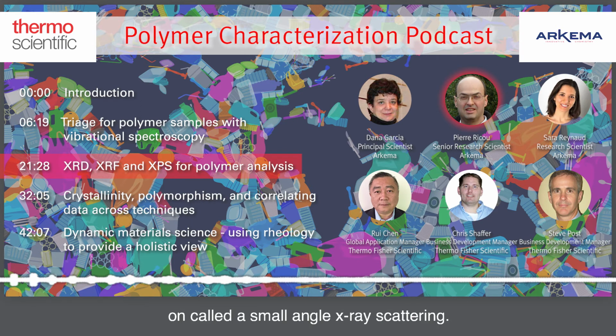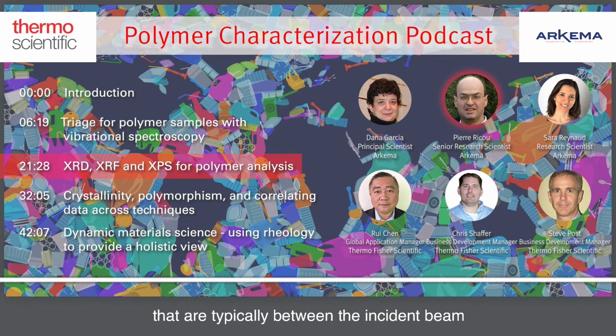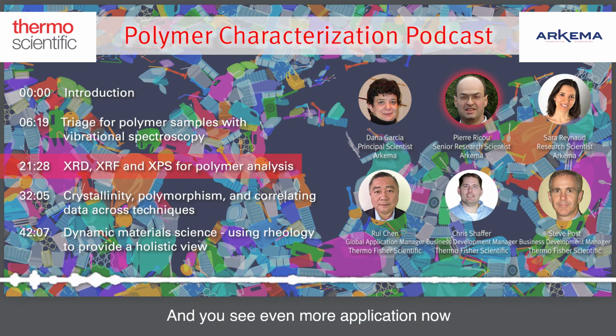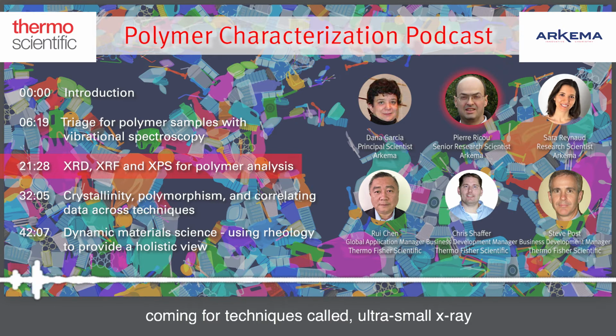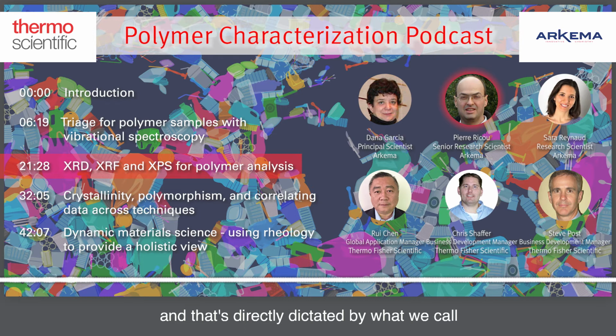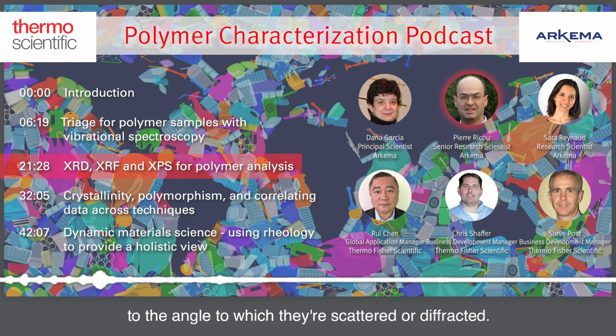A sister technique I want to briefly touch on is called small angle X-ray scattering. So wide angle, as it speaks, you're looking at large angles. Small angle, you're looking at angles that would typically be between the incident beam and a few degrees at most. And there will be applications for the polymer field, and I'll touch base on that. And you see even more applications now coming from a technique called ultra small angle X-ray scattering, which is even a smaller angle where you start looking at larger objects. Basically, when you're talking scattering, there is an inverse relation between angle and the size of the object, and that's directly dictated by what we call the Bragg law. The interatomic spacing in the crystal phases is inversely related to the angle at which they're scattered or diffracted.